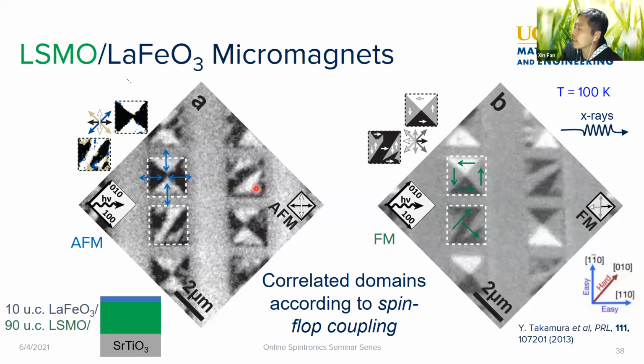Yeah. Do you have an idea of the time scale? Is it on the nanosecond time scale, limited by the ferromagnetic domain speed? Yeah, we have not done that. I mean, any of these measurements are slow measurements because you're actually acquiring spectra. So our measurements are all on minutes time scales. So we don't know how fast the antiferromagnetic spins rotate. Thank you. But yeah, it would be interesting to see if we can get a measurement that gives us time resolution on that.